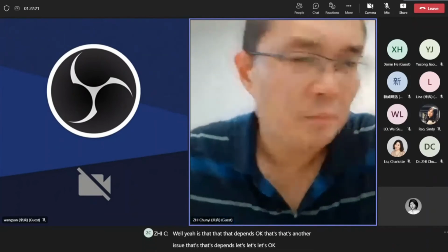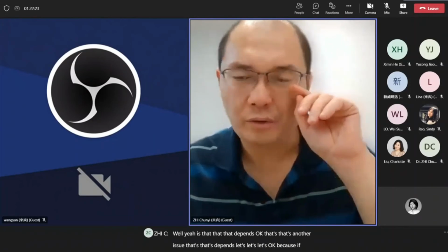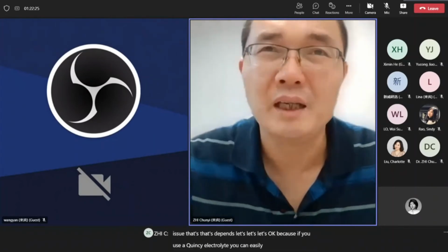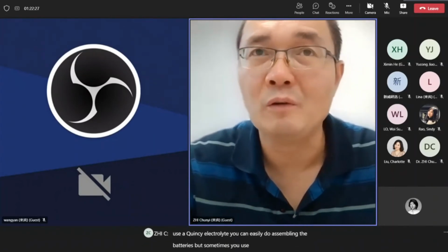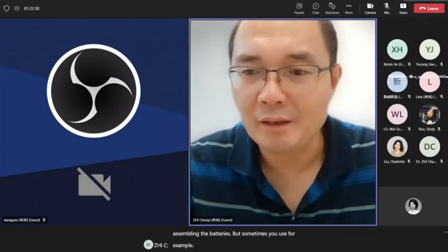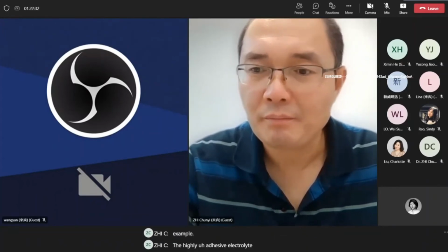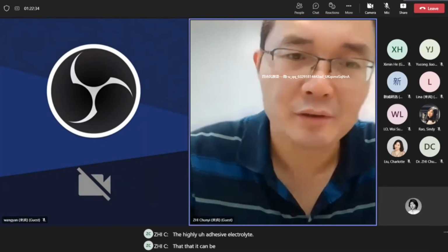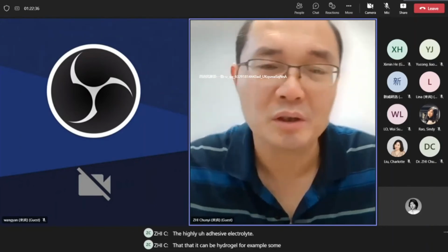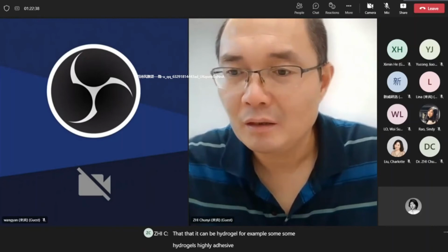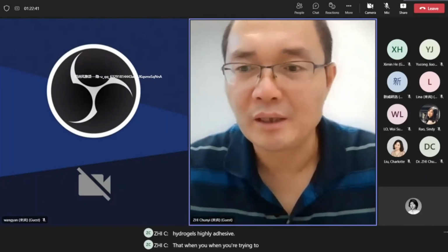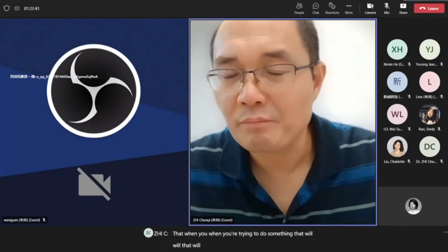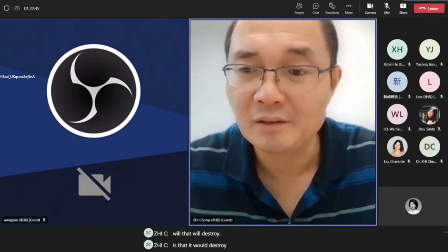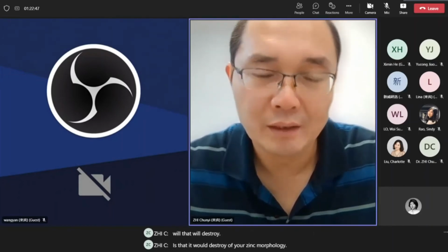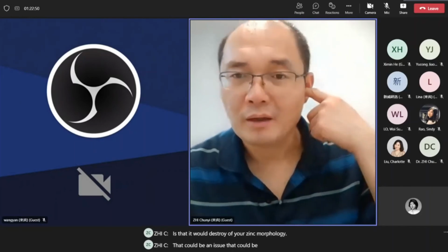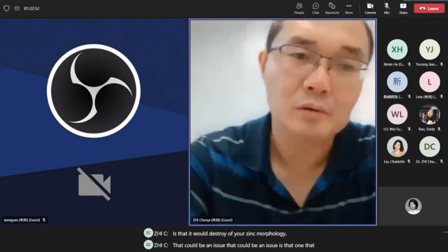That's okay, because if you use aqueous electrolyte, you can easily disassemble the batteries. But sometimes you use, for example, a highly adhesive electrolyte, which can be a hydrogel. Some hydrogels are highly adhesive, so when you try to disassemble, that will destroy your zinc morphology. That could be an issue. I don't have good suggestions for that one.